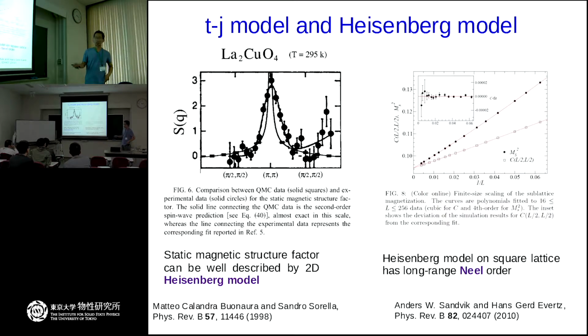And here is a work from Professor Anders Sandvik. The result shows that for the Heisenberg model on the square lattice, there is long-range Néel order. Here is a finite size scaling of the longest correlation function for spin. We can see as we go to the thermodynamic limit, we have a finite value here, which means we have a finite order momentum in this model.